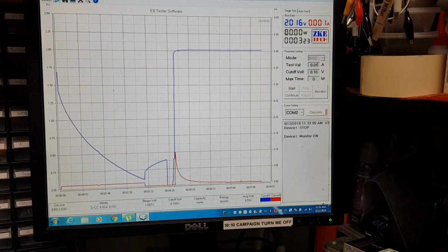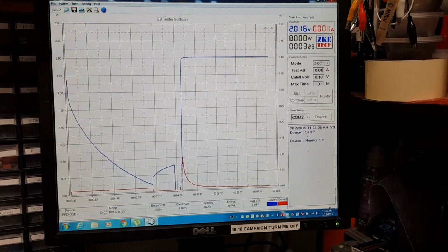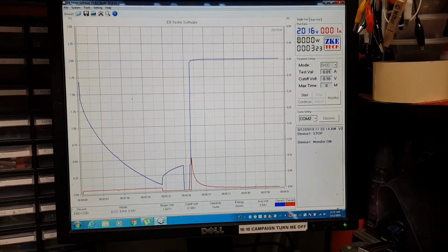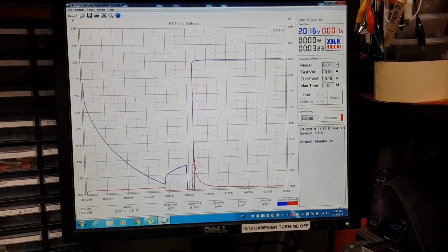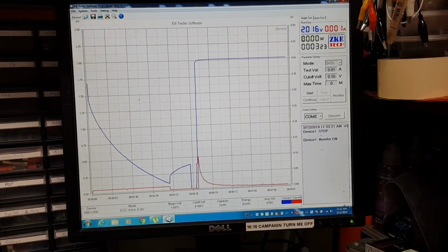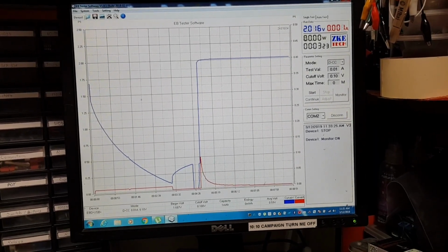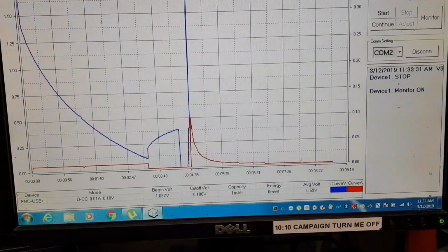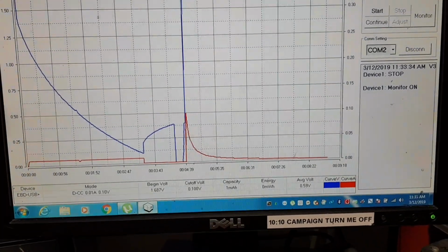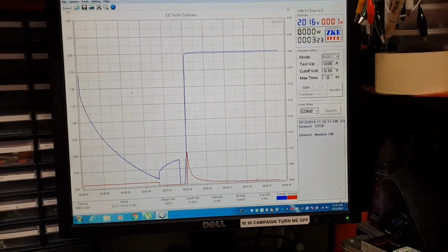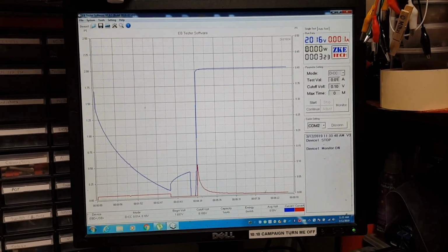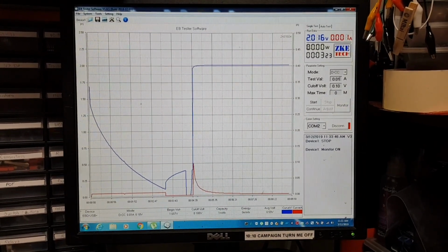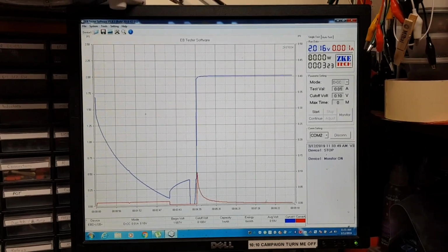The second charge, as you can see, has a nice curve. The current is dropping nicely. It's now on 1 milliamp, and I'll try to charge it for more now. So I started around 4 minutes 40, and I'll try to leave it till 14 minutes, around 10 minutes charge, to see if that is going to change the low performance, if it's going to bring any improvements.